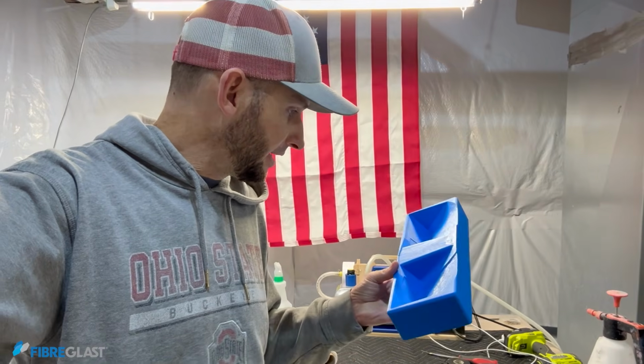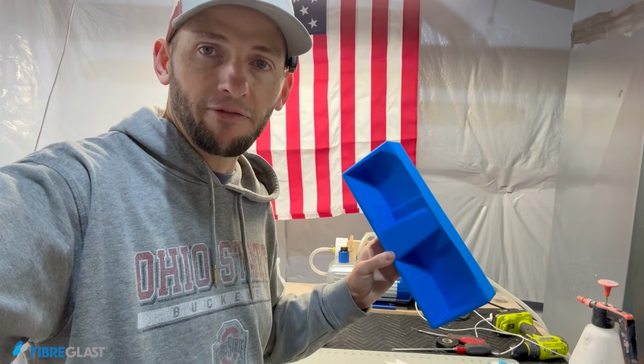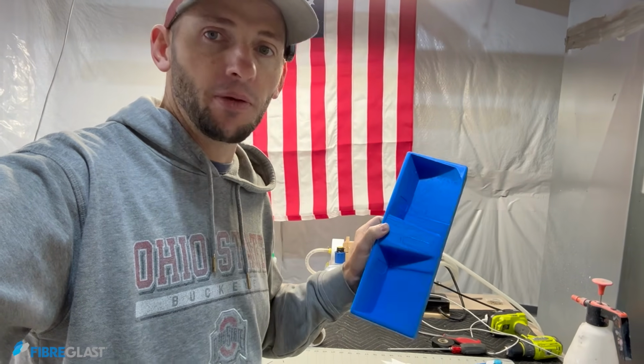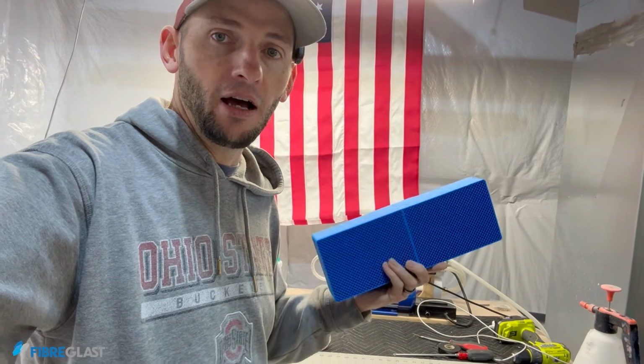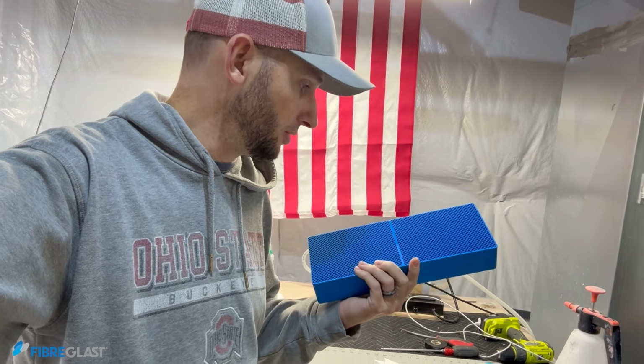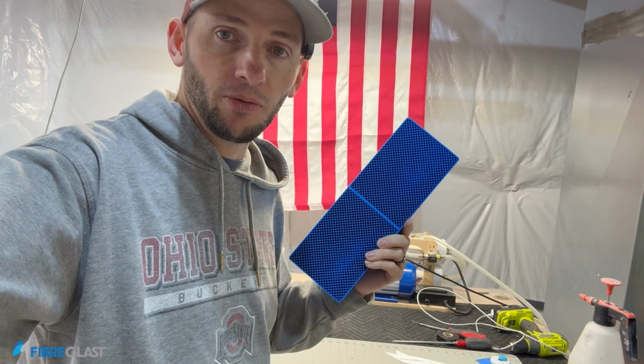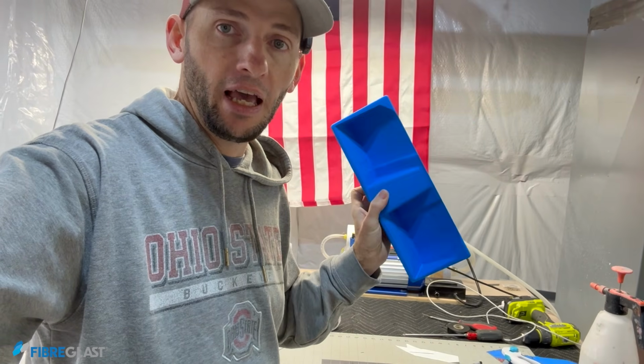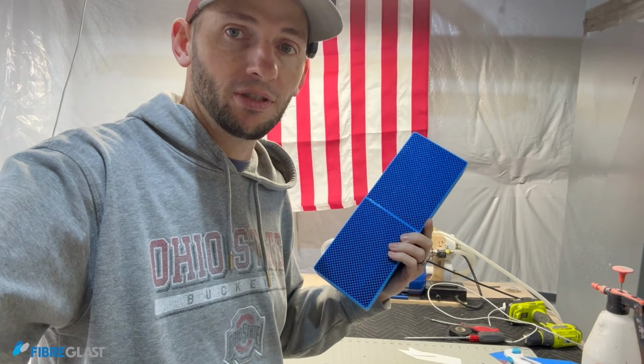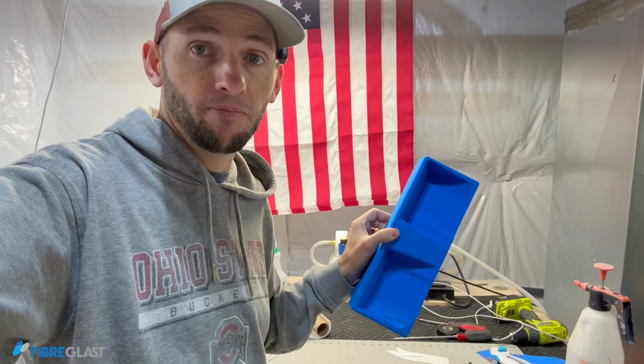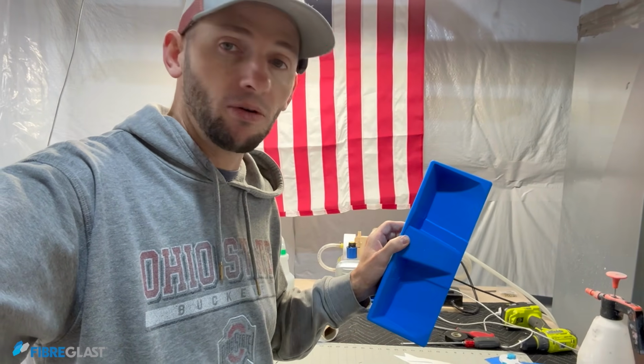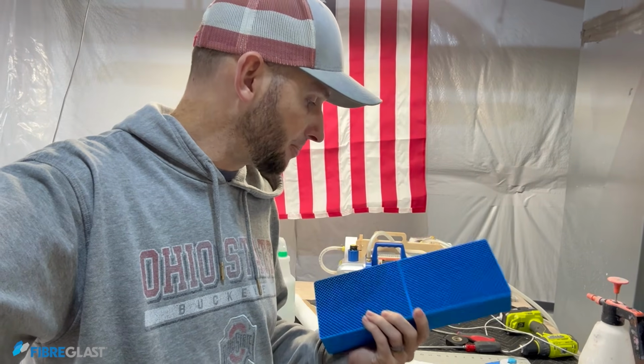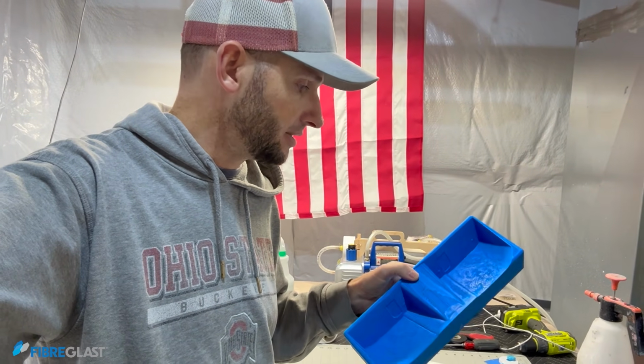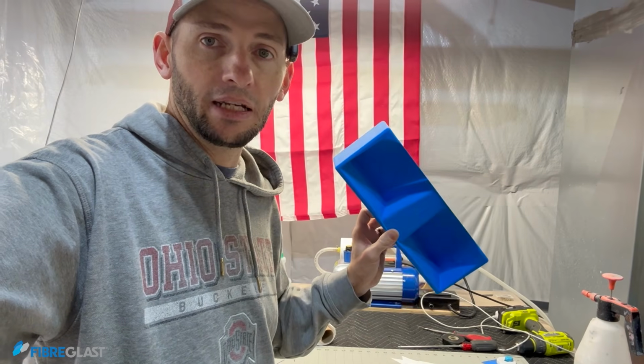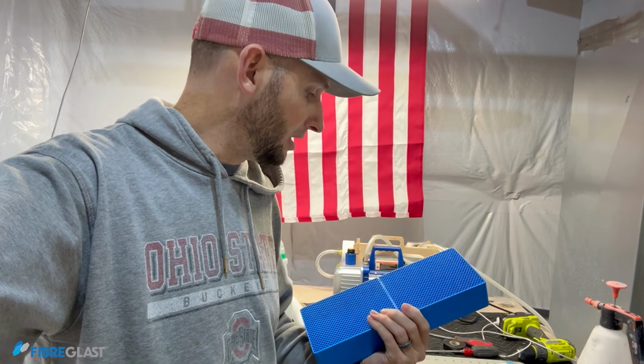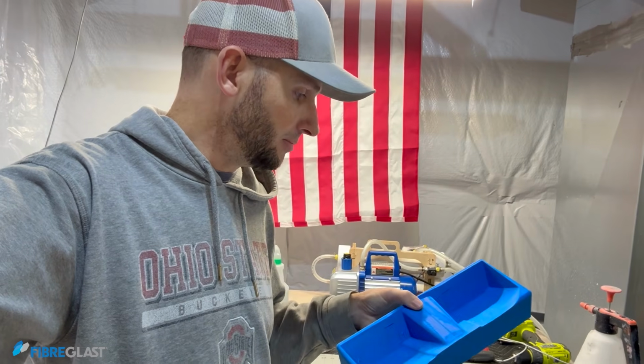So after a lot of thought and to keep with the theme of the least amount of effort to produce a part with 3D printing, I'm not going to seal the face of this mold. The reason you would want to is because since it does have vacuum accessible to the back of the face, and if that face is porous, that vacuum will suck all of that epoxy resin, or some, through the surface of that mold and out of your composite part. My thought process there is the epoxy resin is thick enough, viscous enough, and the holes in the surface of this are probably so small that the amount of loss will probably be very, very minimal. So I'm going to ignore it.